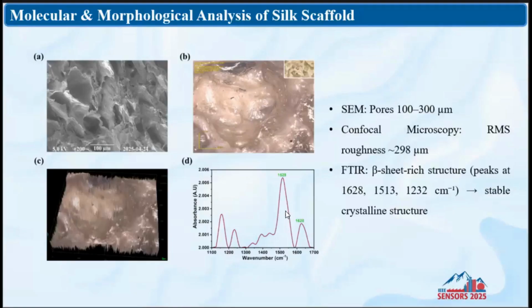And then the FTIR. Usually we use FTIR to know the functional groups and what bonds are there. But here we want to know whether a beta sheet structure is there or not. As per the literature, the beta sheet structure is prominently around 1520 to 1528 wavenumber. It is present, and from the FTIR we confirmed that the crystalline structure of the silk porous structure is present.